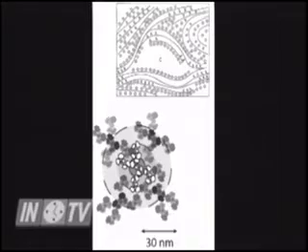Now, one of the important problems with this is that the structure changes a lot if you dry it. Sure. So therefore, if you stick it into a normal electron microscope or into many, many different kinds of instruments, you're altering that structure. So actually the process of looking at it is changing it. It's changing it. So that's one of the reasons why we're still in the state of not fully understanding this much used material. So here we have two pictures, and one way to look at a material is that...